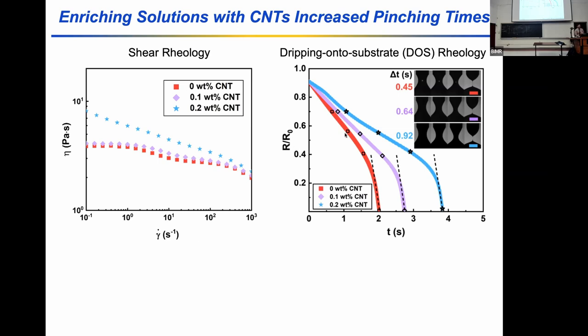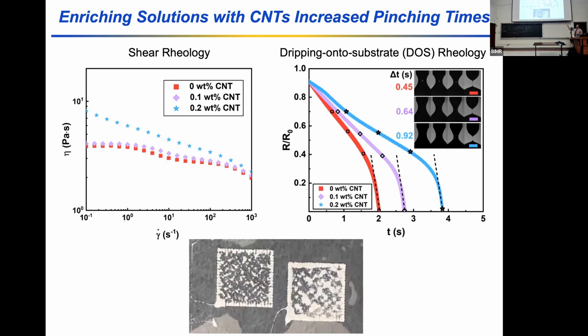But more importantly, the addition increases the extensional viscosity of this solution. And so it delays the pinch off time. And so the way you think about that physically is instead of having little droplets ejected from your printhead, we're able to extrude continuous filaments or continuous tubules from our printhead. And so if we do it poorly and we just extrude droplets, we make a mess like I told you. And so this is a structure that we tried to make from a solution without any carbon nanotubes added.